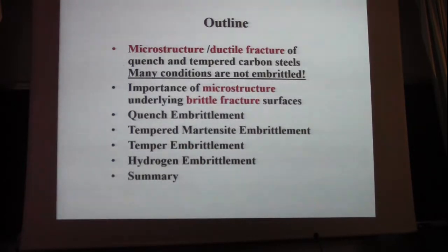Fractography, scanning electron microscopy, very important. It shows us the weakest part of the microstructure relative to fracture. And so underneath these fracture surfaces, where cracking has occurred in steel, there are specific microstructures that we have been trying to identify. And then once I talk about this generally, I will talk about four embrittlement phenomena: quench embrittlement, tempered martensite embrittlement, temper embrittlement, and the all-pervasive hydrogen embrittlement. And we heard a little bit about some of these yesterday. And then a very brief summary.